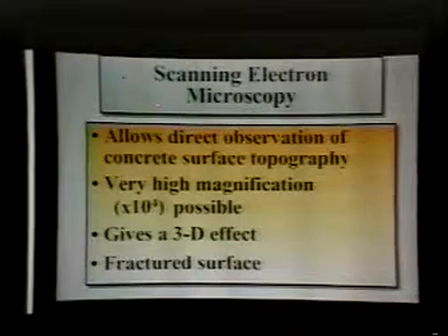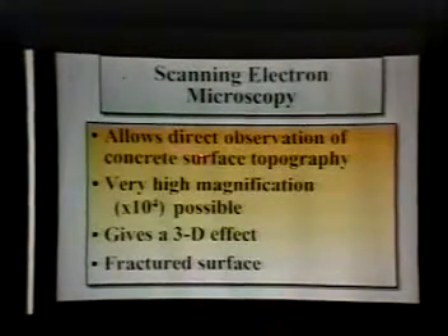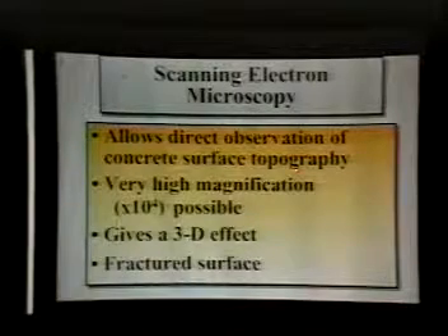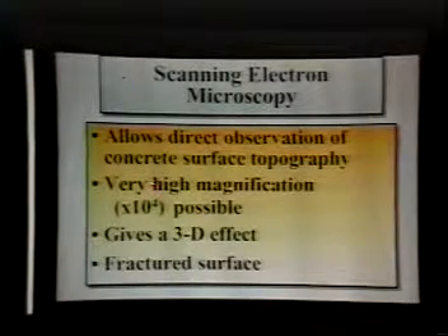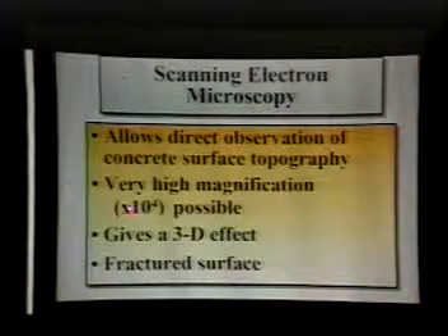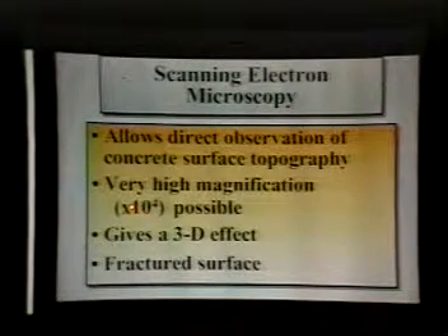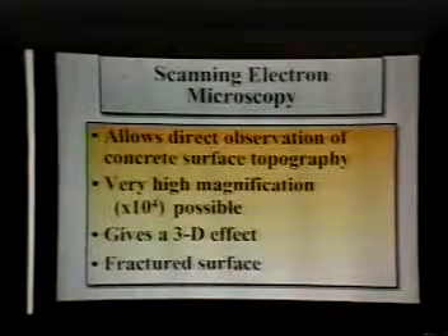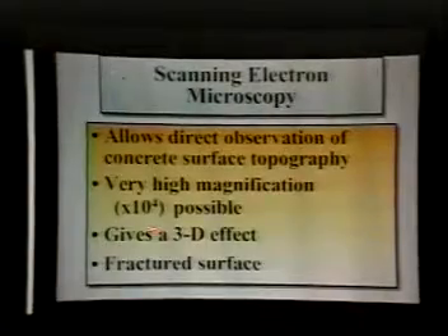Scanning electron microscopy, on the other hand, allows direct observation of the concrete surface topography. You can use a very low magnification to very high magnification. It gives a three-dimensional effect because of the depth of focus. And the advantage is you can use fracture surfaces to examine.